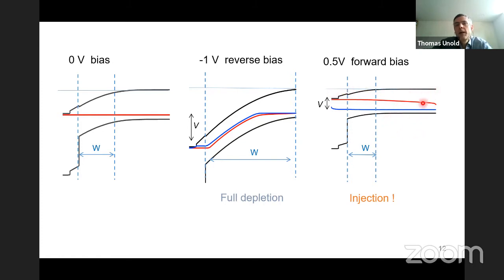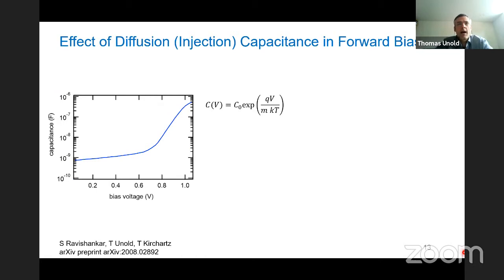But also what I've shown here is the quasi Fermi levels. So this is the electron quasi Fermi level, the hole quasi Fermi level. You can see that here for this 0.5 volt forward bias, you have injection. You have actually now already quite large levels of electrons and holes in the device. And that's not depletion anymore. So the method is not really about depletion capacitance anymore. So let's look at what happens if you have this injection capacitance.